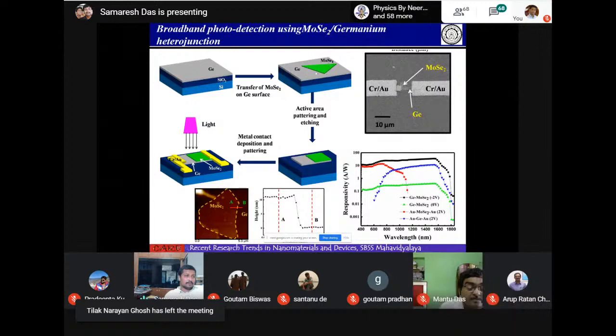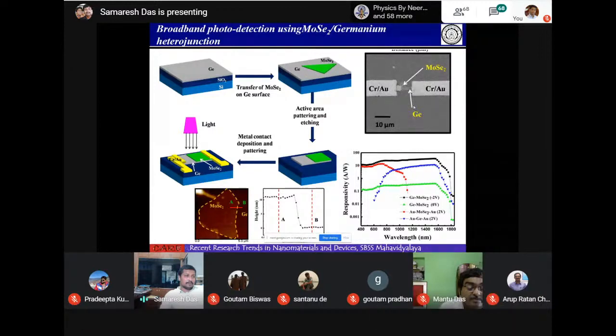So we make the MoSe2 germanium heterojunction. Here we mainly use MoSe2 flakes. By the scotch tape method we transfer them onto the germanium wafer and then make the device by lithography. This is the device, the MoSe2 germanium heterojunction. By making the MoSe2 germanium heterojunction, you can get a very broadband response from 400 nanometer to 1.8 micron. So you can make a very broadband detector using this heterojunction technique.